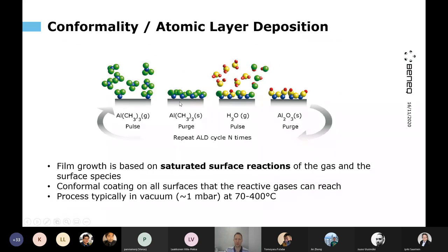So the really good thing is that it makes very high quality films, pinhole free films, and conformal on whatever the surface structure is. And the not so good thing is that it is rather slow, because doing all these things, we get one angstrom of growth. So to make a 100 nanometer film, we need to repeat these steps 1,000 times. In practice, this one ALD cycle takes, depending on the configuration and setup and batch size and many things, anything from between 1 second and 1 minute, typically. So most commonly, some seconds.